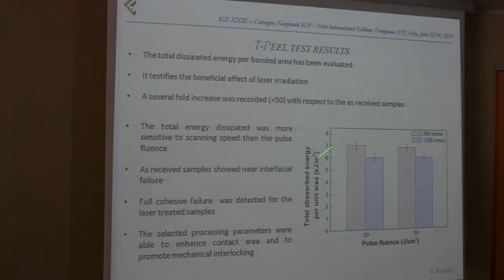Another thing that we could verify during the test was that the laser-treated samples always had a cohesive failure, so within the adhesive, while the as received showed a near interfacial failure. So of course this is another sign for us that seems to confirm that the laser treatment is improving the joint. Here it is not reported, but we also performed tests by sandblasting the materials, and we still had around half of the energy absorbed compared to the laser treated.